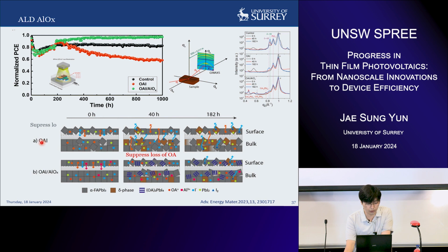So this is the schematic of what happens under continuous illumination. With OAI alone, continuous illumination induces the evaporation of the iodines and OA cations. So the material just evaporates and we lose this material and the structure collapses. However, if you have aluminum oxide, we suppress the loss of the volatile species and sort of trap these ions. And these ions under continuous illumination will self-form a 2D layer. So that's the 2D layer here, which is formed at the very top surface and also some in the bulk as well.